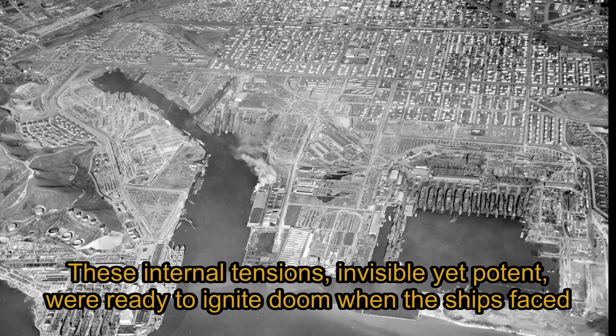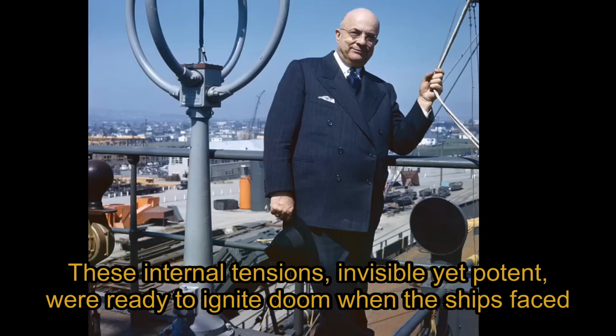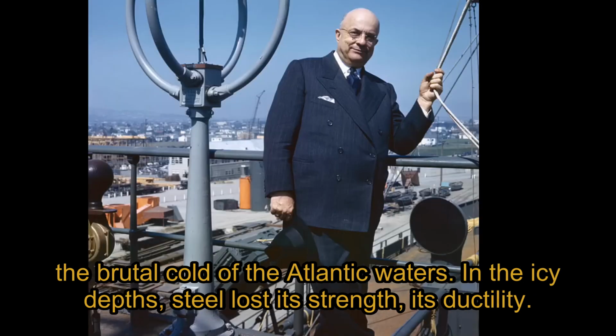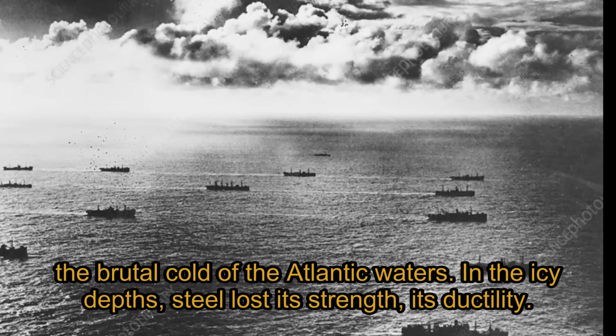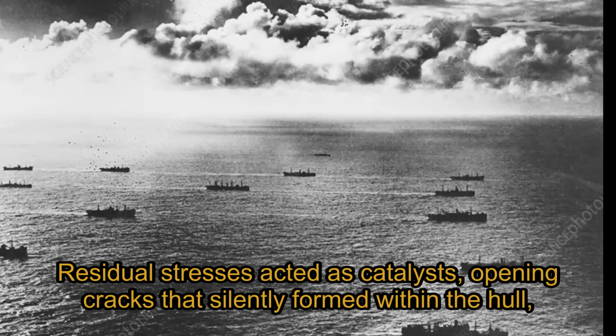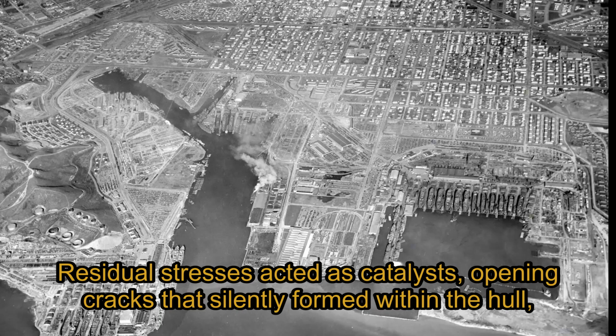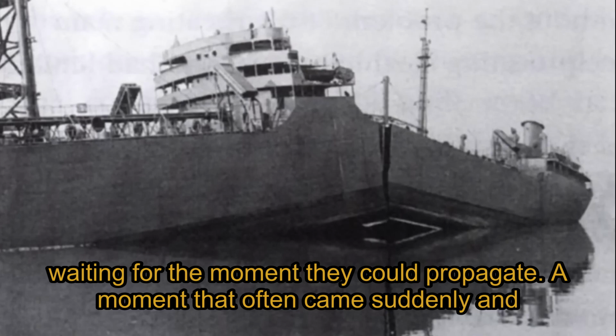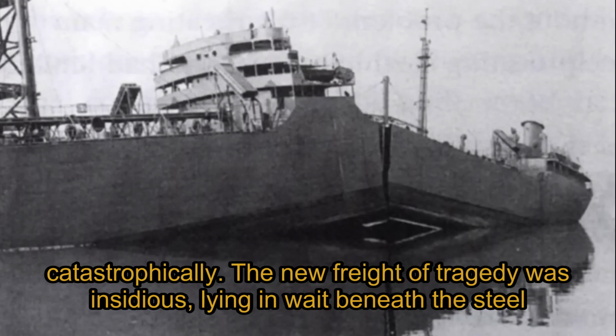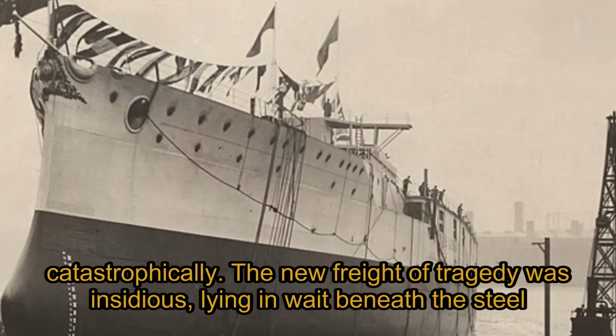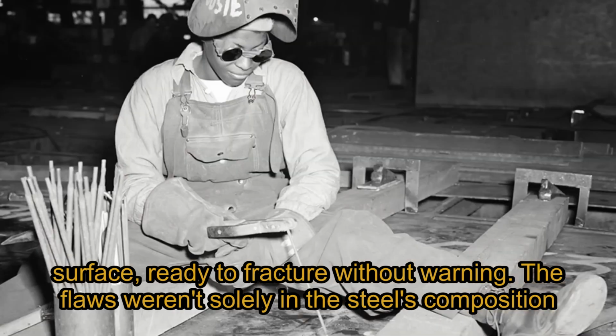These internal tensions, invisible yet potent, were ready to ignite doom when the ships faced the brutal cold of the Atlantic waters. In the icy depths, steel lost its strength, its ductility. Residual stresses acted as catalysts, opening cracks that silently formed within the hull, waiting for the moment they could propagate, a moment that often came suddenly and catastrophically. The new freight of tragedy was insidious, lying in wait beneath the steel surface, ready to fracture without warning.